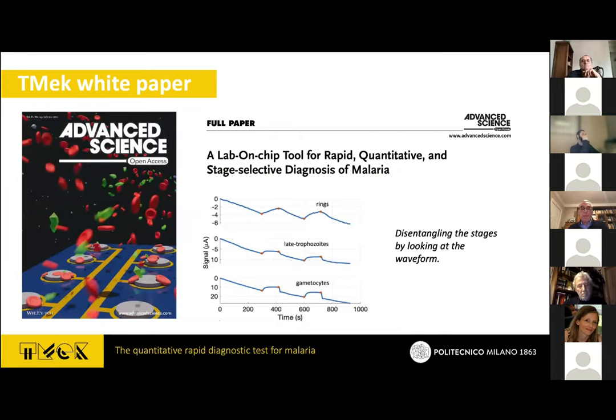So saying that, okay, it works. We also discussed the possibility to disentangle the different stages by looking at the waveform because rings, late trophozoites, and gametocytes give rise to different waveforms when you move the magnets up and down. This is due to the ratio between the gravity force and the magnetic force, which will depend on the stage. So if the magnetic force is very high, each transition will be sharp because the effect of the magnet approach or the disengagement will be seen very, very fast. If you are dealing with the parasite at the early stage, the content of the hemozoin is small, so the magnetic force is small. And in this case, each transition will be much smoother. And this is something that can be used.